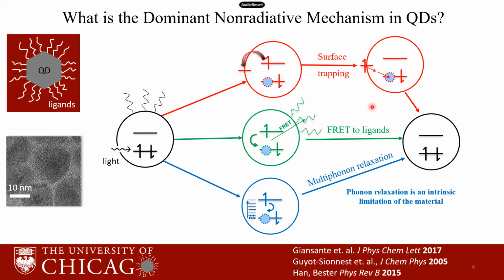Over here, it is important to emphasize that among these three mechanisms, the first two can be overcome by engineering the surface of the quantum dot, either by removing the defect states on the surface or by changing the surface ligands. But since phonon relaxation is intrinsic to the material, there is nothing that can be done to overcome this. And this would be a dead end to the performance of quantum dot detectors.